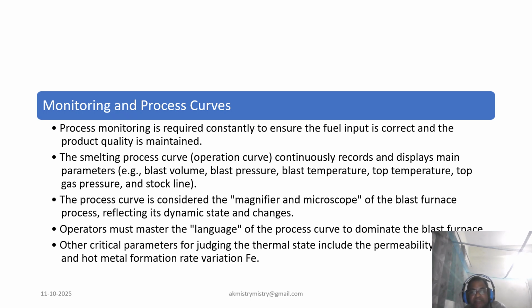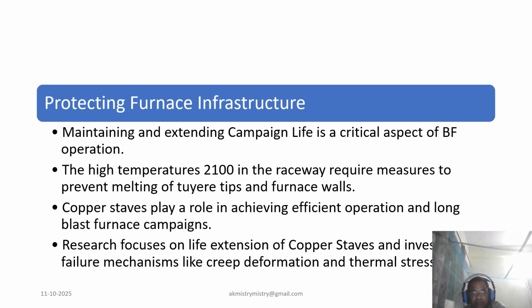Process stability is critical for equipment integrity, with the raceway temperature reaching around 2100 to 2200. Protective measures like copper cooling staves are used to minimize heat losses on the shell. However, these staves are susceptible to significant fluctuating thermal load.